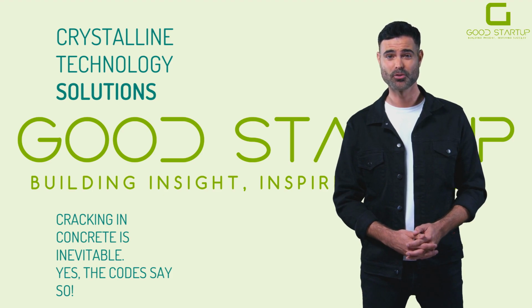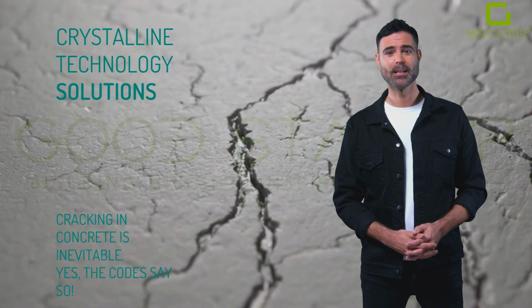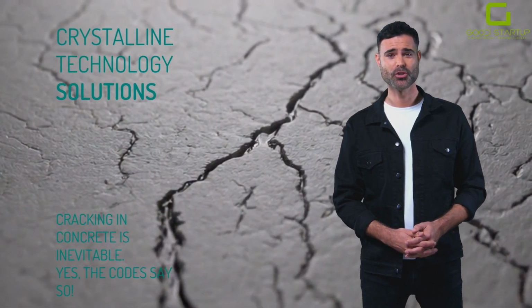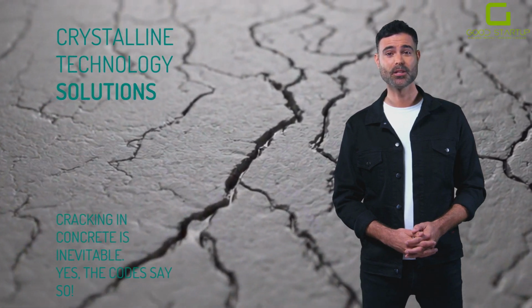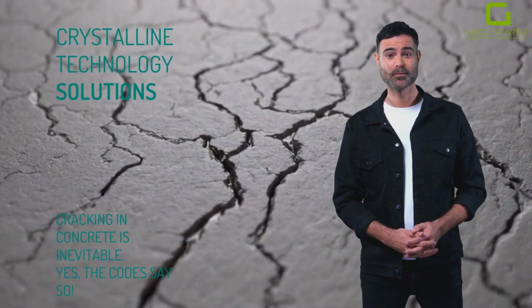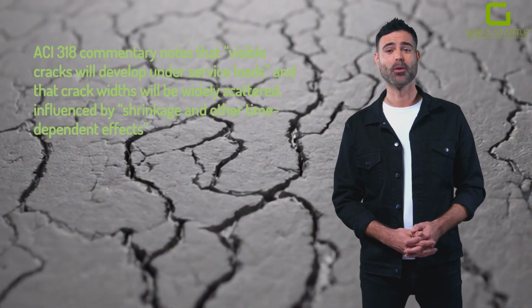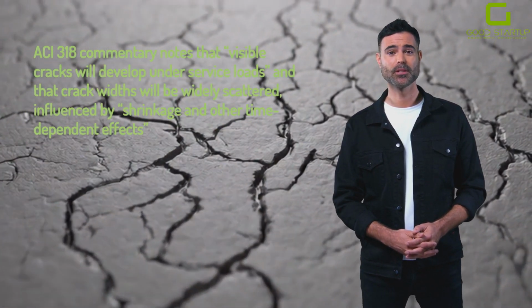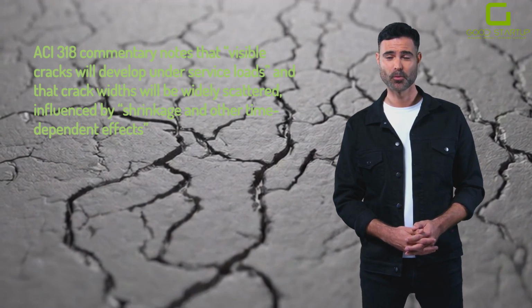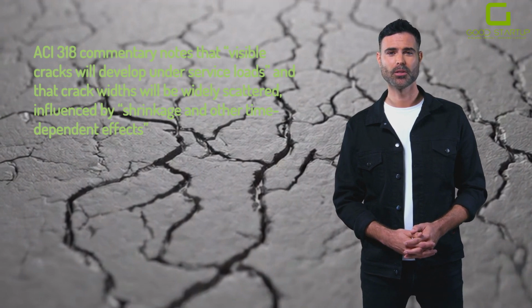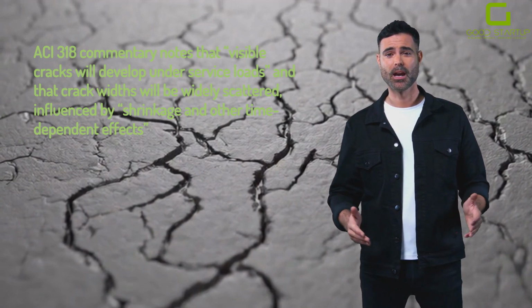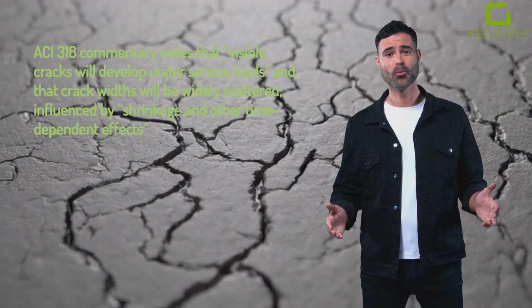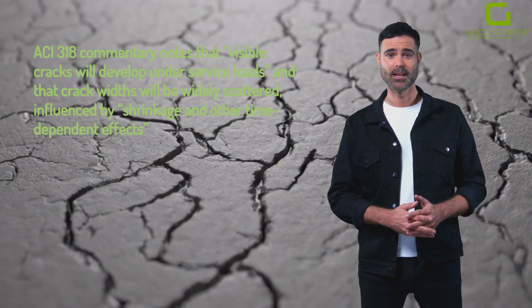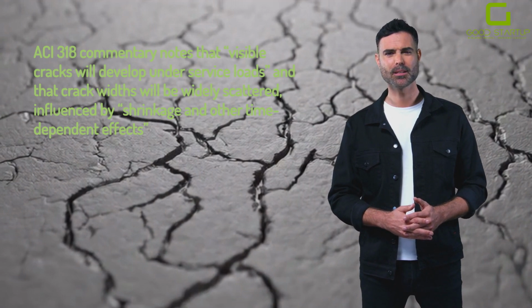It may sound counterintuitive, but every experienced engineer knows that some cracking is expected in reinforced concrete. Our design standards openly acknowledge this. For example, ACI 318 commentary notes that visible cracks will develop under service loads and that crack widths will be widely scattered, influenced by shrinkage and other time-dependent effects. In other words, even with proper design, we should expect hairline cracks in service.